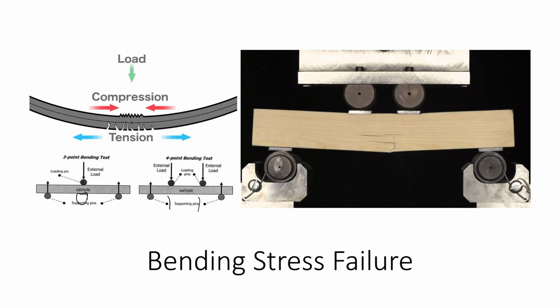We typically use the 4-point bending test for more brittle materials. Compared to the 3-point bending test, there are no shear forces in the 4-point bending flexural test in the area between the two loading pins. So it's a better test for brittle materials that don't withstand shear stresses very well. The advantage of the 3-point test, however, is that the sample is easier to prepare and to test, but unfortunately, like I said, it is sensitive to loading geometry and strain rate. But if you want a beam to hold loads, you are going to need to have a high flexural strength.